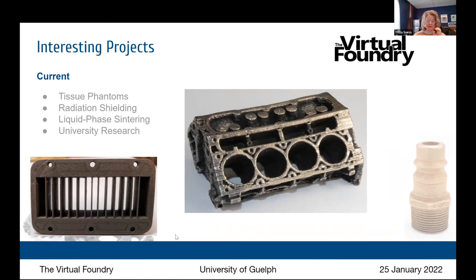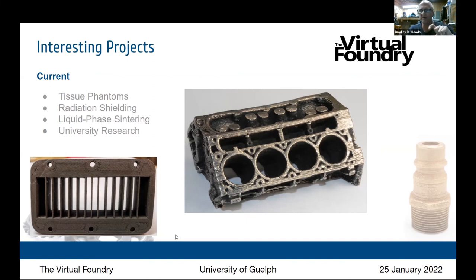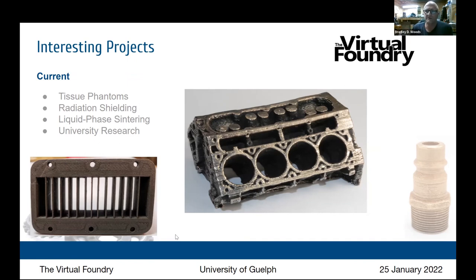In liquid phase sintering, the bronze melts before the steel sinters. You put bronze powder in contact with the steel part in the kiln, and as the temperature rises the bronze melts and gets sucked up into the steel part via capillary action, filling all the space. Brad put a sprue or stem out the bottom and placed a small container of bronze — as it melted and everything heated up, the stainless steel soaked up the metal like a sponge. Capillary action carried the bronze from the bottom of the part to the top — as much as seven inches — with no problem.